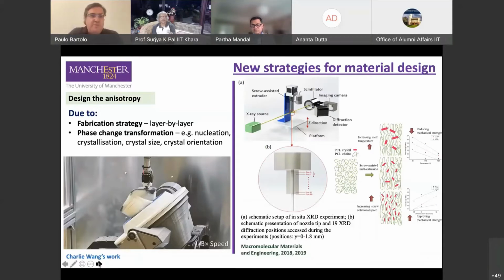So in the case of polymers, for example, we start with a material in a solid state, then we heat the material, and the material is then cooled down. And during this process, there is a morphological change, and depending on the cooling process, and also depending on the temperature used to melt the material, all of these conditions affect the crystallization mechanism, crystal size, crystal orientation, and this has an impact on the anisotropy. My group, the manufacturing group, is focusing on all of these aspects.